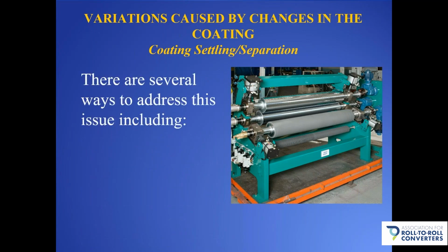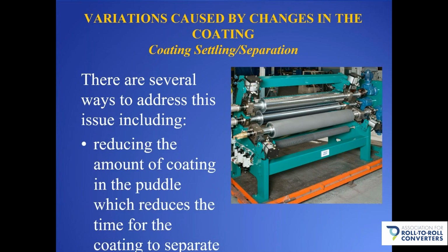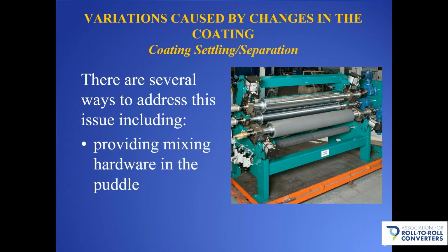So how do we address this issue? Well, much like we talked about earlier, you can reduce the amount of coating in the puddle, which reduces the time that the coating has to separate. Or you can provide mixing hardware in the puddle, which continuously keeps the solids in solution or in suspension.